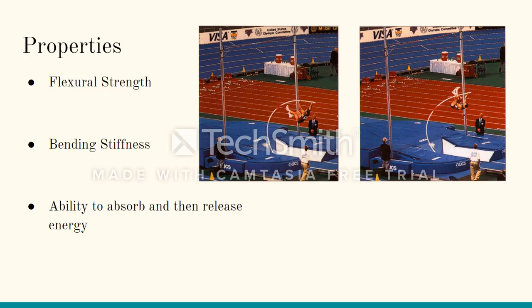In flexural strength, the stronger the pole, the more weight is required to bend the pole. This means larger individuals or faster runners, with kinetic energy being the key operative term, can use heavier poles. A pole vaulter simply does not want an easily bendable pole, as the pole will not be able to release that energy quickly and achieve a higher jump. However, a pole vaulter does not want a brittle pole, as it can snap while vaulting.